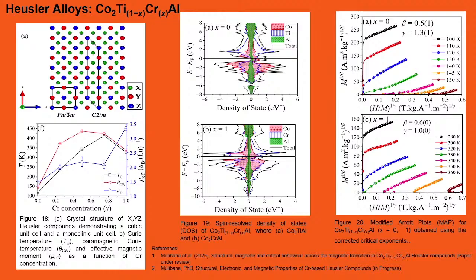These metals are ferromagnets, so they all align, in this case like iron, but when we start adding chrome to it, we can see the transition temperature in this case increases, and at this point, at 0.75 chrome, it decreases. While the spin moment, the effective moment, still increases, and we're not totally sure. We're still trying to figure this out. There's a lot of questions about why.